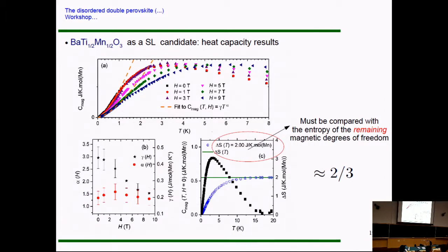So, then that being said, I turn to the analysis of the heat capacity data. Here I just fit a power law behavior. And as you can see, the alpha exponent is pretty much constant within the error bars, and the average here is about 1.4 if you do the calculation.